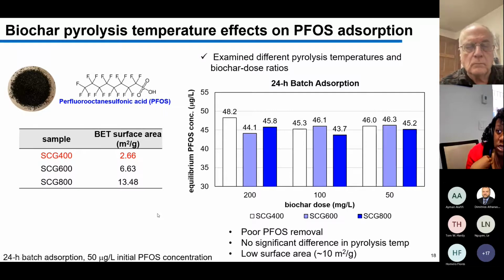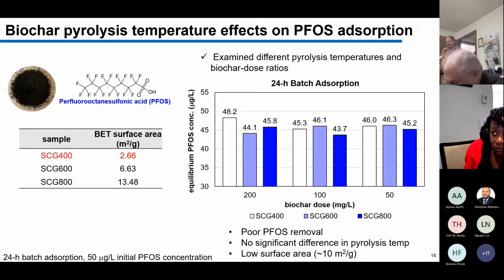So what we did next was we took advantage of knowledge around pyrolysis of other carbon-rich materials, in particular, the activated charcoal that's used for water and wastewater treatment. So the activation step can be done in a bunch of different ways, but during activation, what you're doing is creating more surface area within the material by doing an additional pyrolysis step in the presence of some chemical activating agent that allows for this increased surface area, which we hoped would help improve PFOS removal.